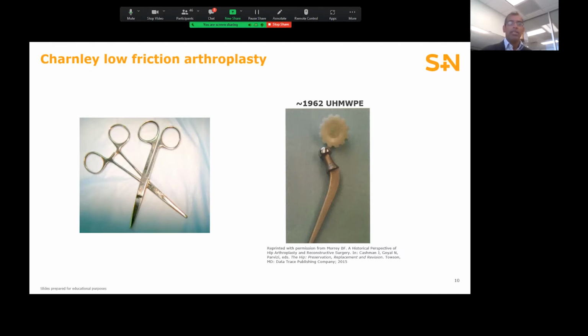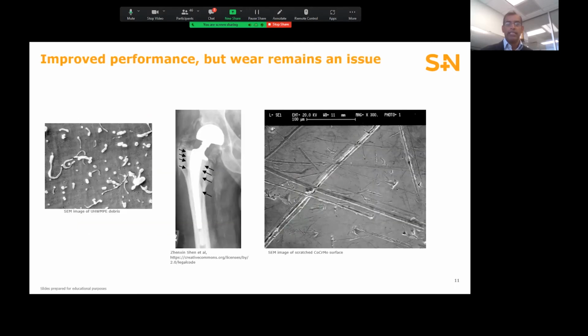And despite recording some early symptoms at the implantation site for PTFE, he persisted with the experiment up until 9 months. And at that time, he recorded that he could distinctly feel nodules around the site of PTFE implantation, and that those nodules were about twice the size of the material he had implanted. In contrast, the UHMWPE site was much less distinct. So after this experiment, Charnley began implanting UHMWPE acetabular components paired with cobalt chrome femoral heads. And based on his successful outcomes, others followed suit. While designs varied, polyethylene paired with cobalt chrome heads were widely implanted for subsequent decades, and Charnley's pioneering work in this area is widely recognized. He was actually knighted in 1977 in recognition.